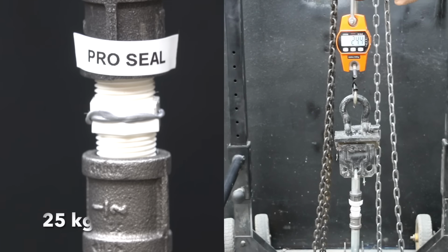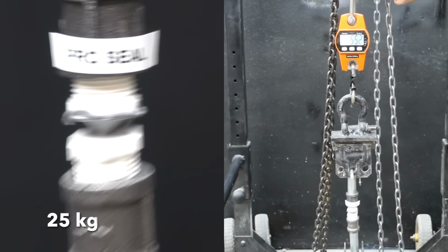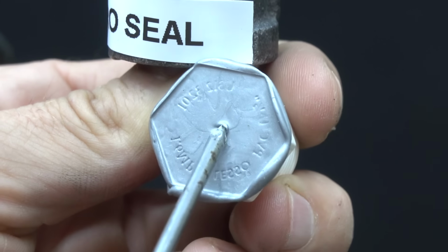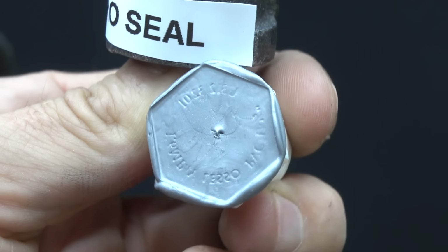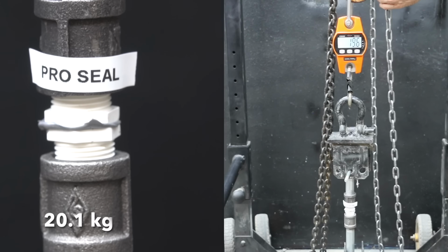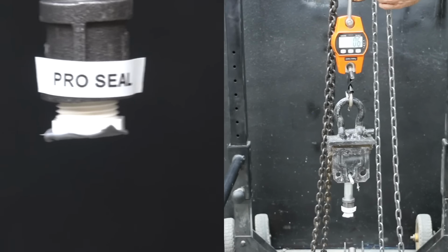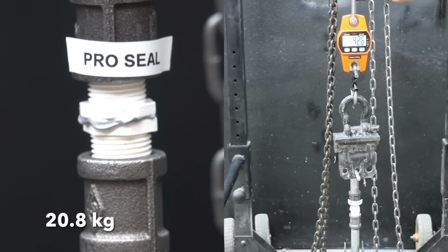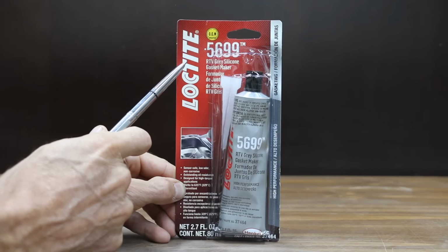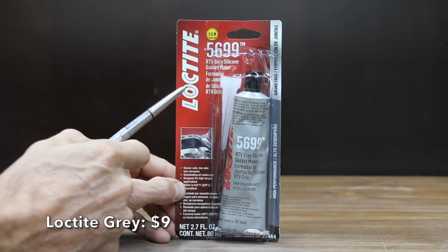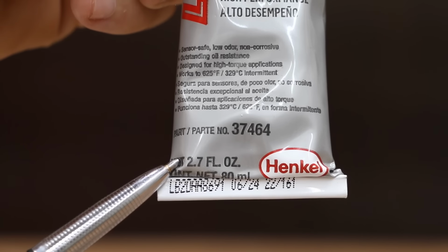And the Pro Seal performed about the same as the JB Weld on the first test piece at 55.2 pounds. Even though it didn't have as much tensile strength, it's almost completely cured. And the second test piece isn't quite as strong as the first at 44.4 pounds. And the third test piece is almost the same as the second at 45.8, for an overall average of 48.5 pounds.